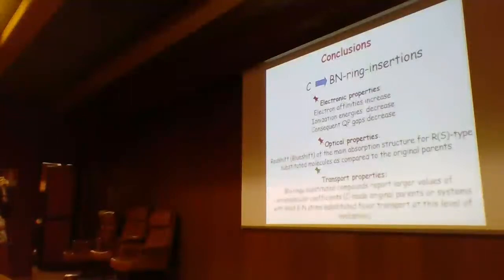And finally, for what concerns transport properties, at this level of evaluation, without the computation of the full set of transport coefficients, but limiting our analysis to lambda, the molecular reorganization energy, our hypothesis is that carbon-made original parents or systems with a small amount of boron and nitrogen inserted into the matrix favor transport.